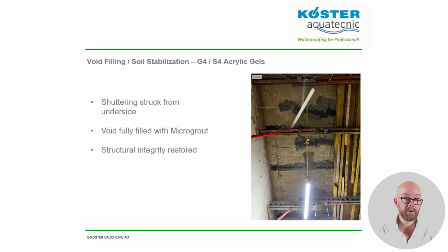After 24 hours, shutters were removed, the packers snapped off, and the boreholes filled flush using a fast-setting mortar. The image shows the repair immediately after the shutter was removed. The microgrout looks darker than the surrounding concrete, but as it cures, it becomes lighter. This type of large structural repair can really only be done using a microgrout. With a troweled repair mortar, it would be impossible to fill all the gaps around the rebar. An epoxy resin used in this volume would generate too much heat, causing it to then shrink back as it cooled.